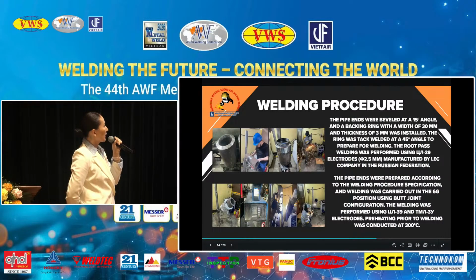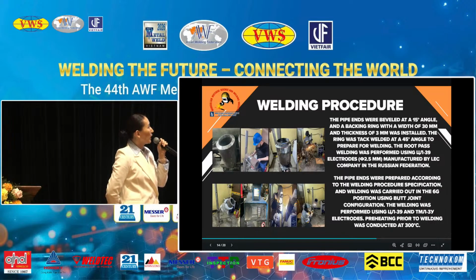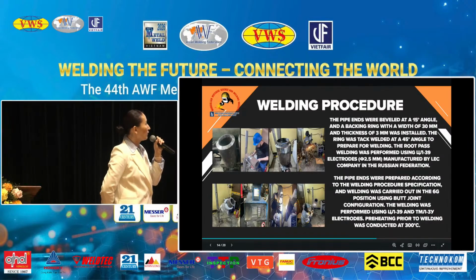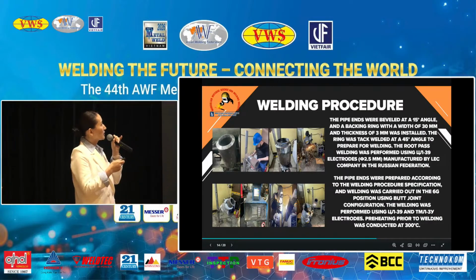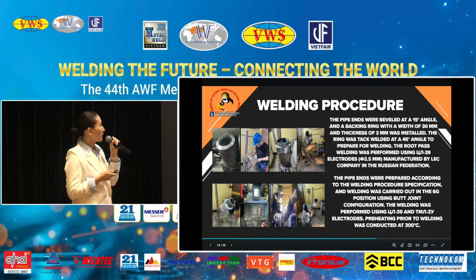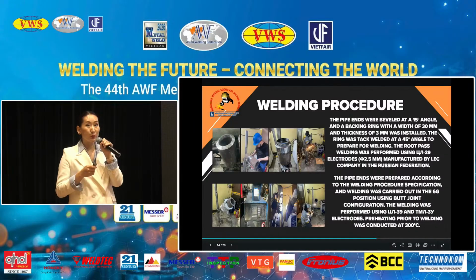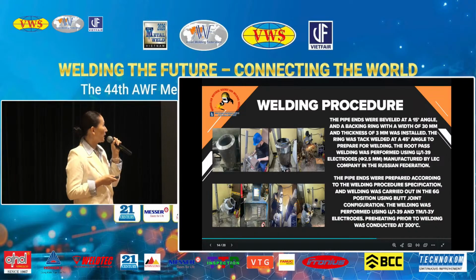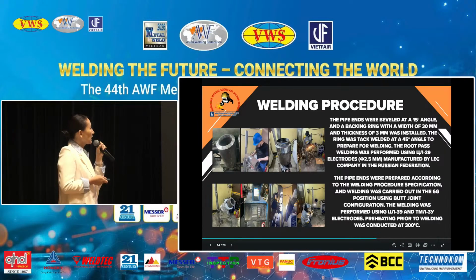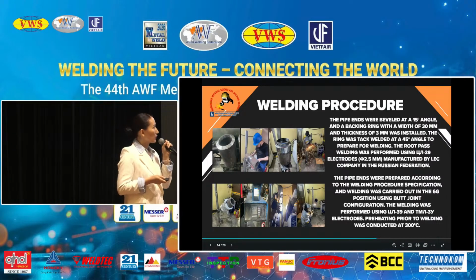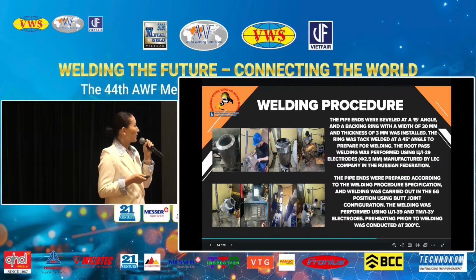For the welding procedure, the pipe ends were beveled at a 15 degree angle and a backing ring with a width of 30 millimeters and thickness of 3 millimeters was installed. The ring was tack welded at a 45 degree angle to prepare for welding. The root pass welding was performed using LJ-39 electrodes of 2.5 millimeters, manufactured by a company in the Russian Federation. The second line: pipe ends were prepared according to the welding process specification, and the welding was carried out in the 6G position using the butt joint configuration.